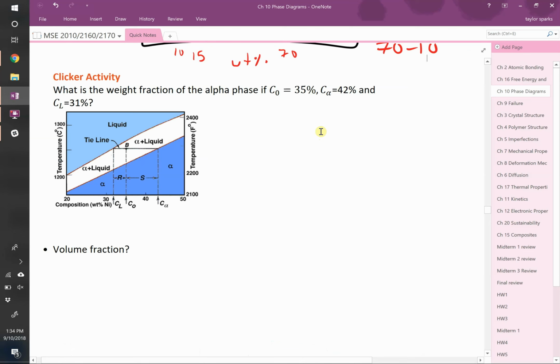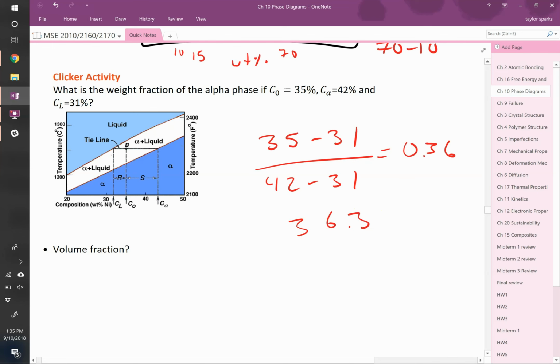Since we want alpha phase, that's the phase on the right, we're going to take the left-hand tie line, right? Our initial composition C naught is 35, so the left-hand side is going to be 35 minus 31, divided by the total length, which is 42 minus 31. I get 36%. That equals 0.36, a fraction. If you want to turn that into a percent, multiply by 100 and you get 36.3. This is in weight percent nickel, so that's going to be weight percent alpha. Any questions, Ashton?